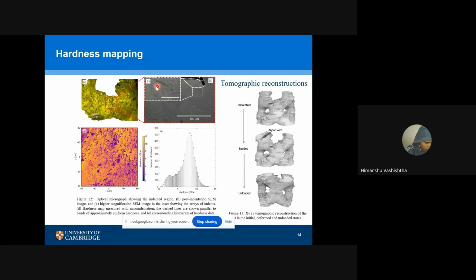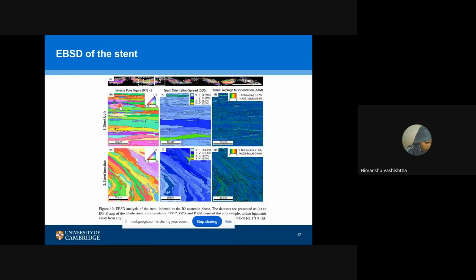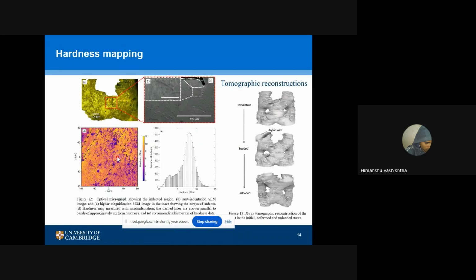So we have mapped the hardness of this whole area by placing the indent at a proper distance, and in a series of hardness mapping, we have created a map. Here you can see diagonally at this junction, we are getting a pretty good amount of hardness. It's because when you have seen the EBSD map, in this region, particularly where the junction was, a high amount of dislocations was there. That means the defects were there, and higher defects lead to higher hardness. The average hardness was somewhere around 8 gigapascals, and that's well within the already documented hardness for additively manufactured components.